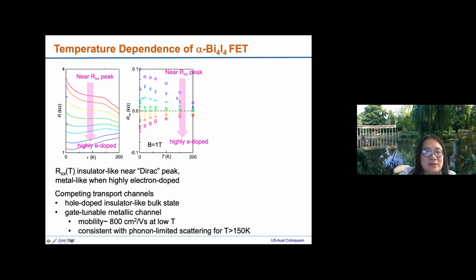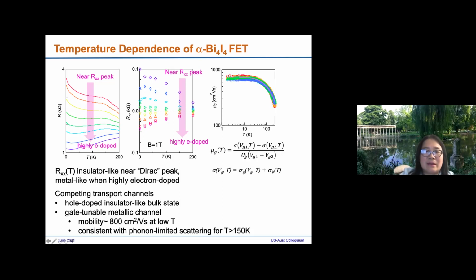From looking at this, we conclude there are two competing transport channels. One is the hole doped insulator-like bulk state, which is basically independent of the gate, and there's a gate tunable metallic channel. So what we can do is subtract the curves from each other, which should eliminate the gate independent bulk state. Then we divide by the difference in gate voltage and by the capacitance between the gate and the sample, and the curves collapse into a single curve. This is pretty good. It tells us the mobility of this gate tunable channel as a function of temperature. At low temperature the mobility is about 800 centimeters squared per volt second, and it decreases at higher temperature, consistent with phonon limited scattering.